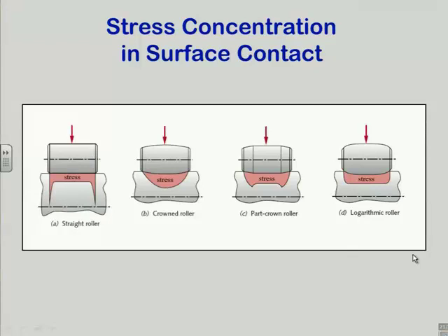Now you say, where's the notch? You've told us before, Professor Norton, that you always have high stresses at a notch. Where's the notch? Well, there isn't a physical notch here. There's a stress notch, if I can call it that, because suddenly the stress goes from something to nothing. And if you imagine that material is being actually deflected down over the length of the roller, that's the notch: the slight change in contour of the physical part, which is almost too small to see.